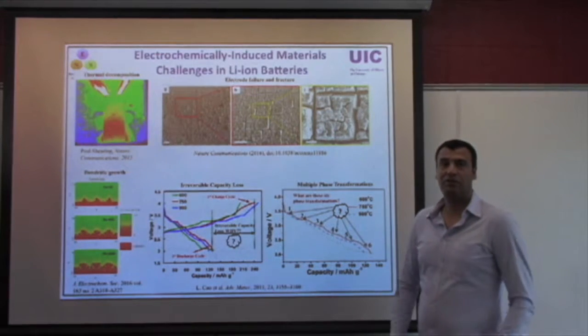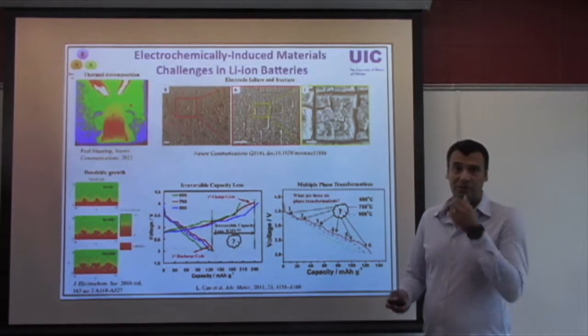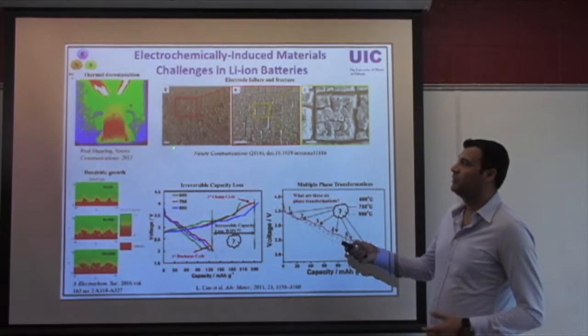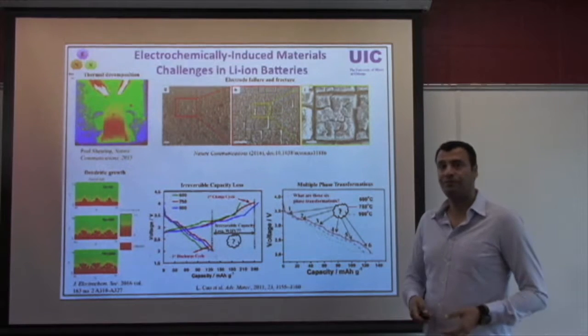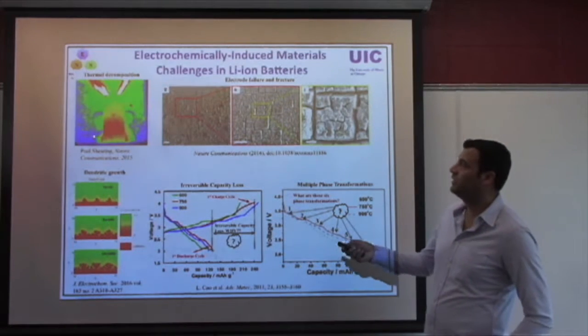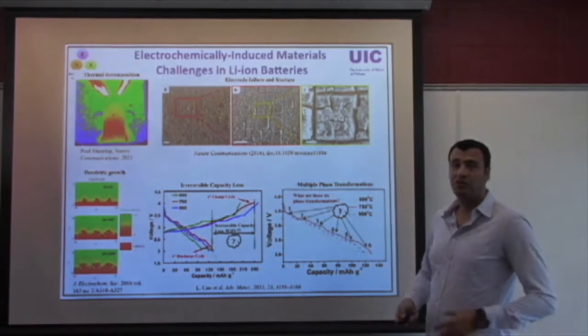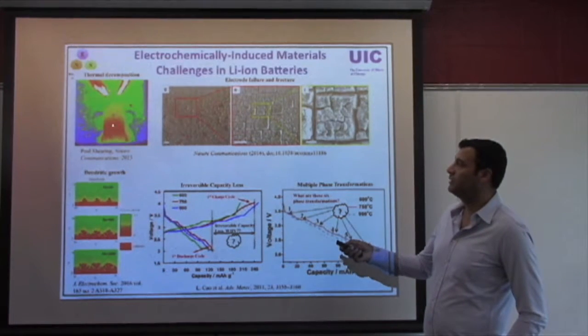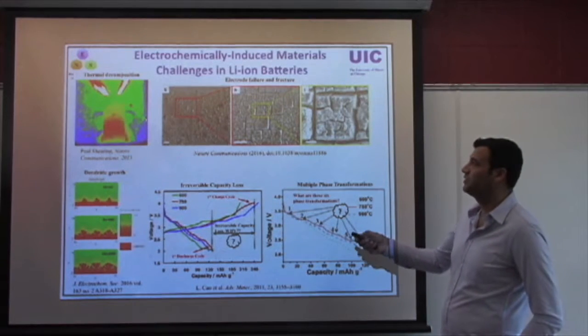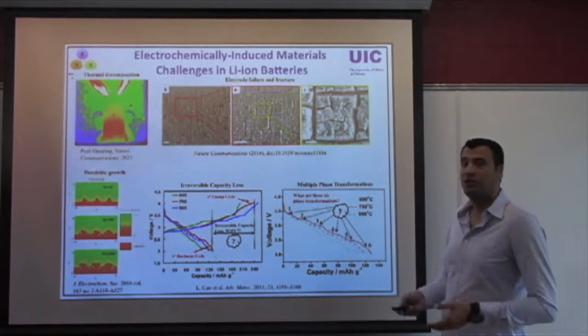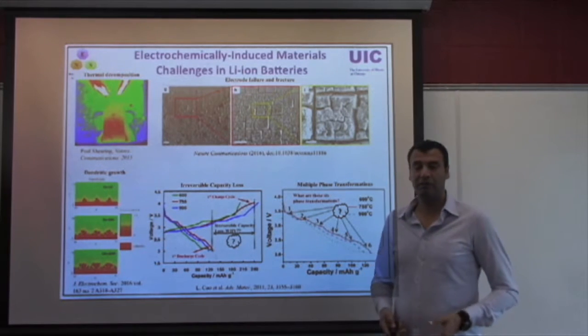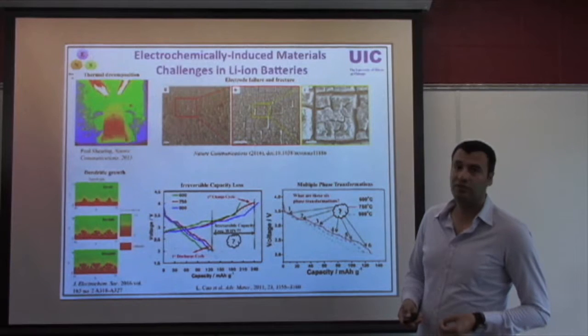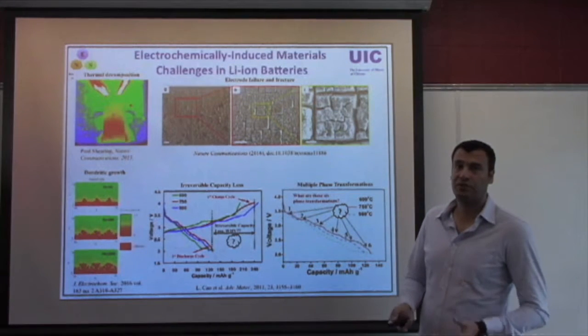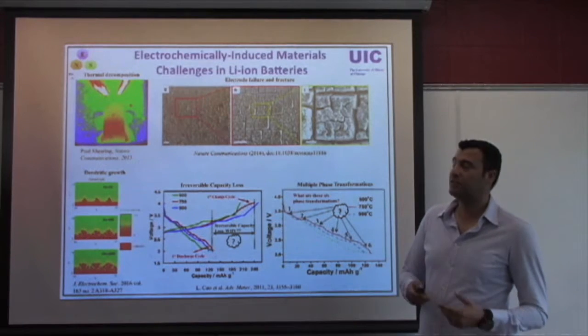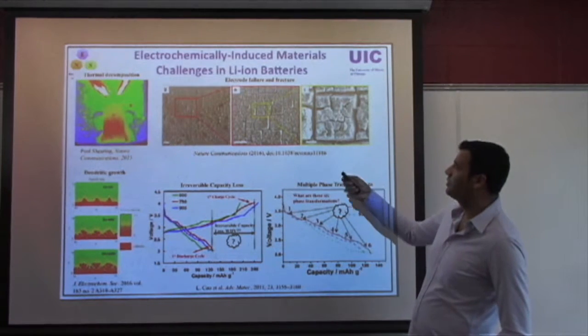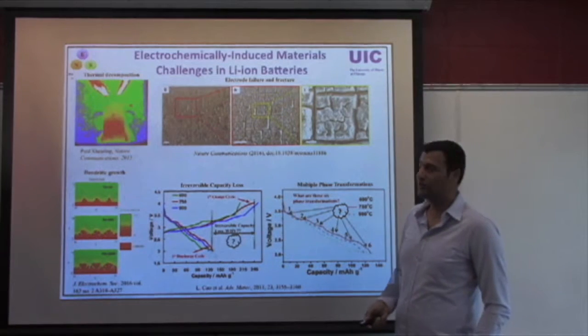Examples of, for example, a thermal runaway issue in batteries involve several chain reactions from SEI decomposition to electrolyte decomposition and eventually electrode decomposition, which we need to understand and find better mitigation strategies to address this issue. Another issue in electrochemical battery devices is that we have a lot of volume expansion and stress generation due to the intercalation of ions within the structure, which eventually results in cracks and failure of the electrodes.